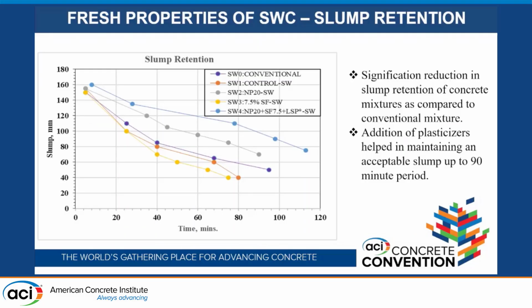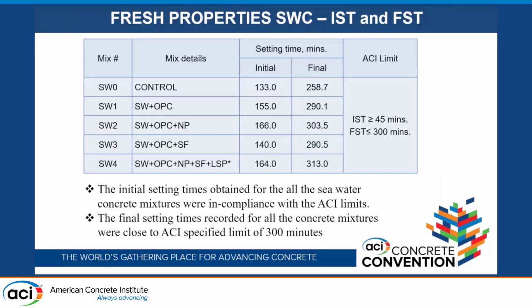Thus, coming to the fresh properties of this seawater concrete, because as mentioned earlier by Professor Nani, slump retention is a very important issue, so that was investigated for all the concrete mixes, and as you can see, there is a significant reduction in slump retention of the concrete mix as compared to the conventional mix. However, addition of plasticizers helped in maintaining the acceptable slump through almost a 90 minute period. So that required a lot of trials and changes in the mixes.